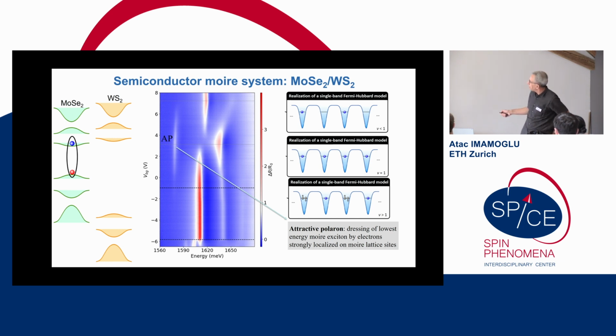Now, as we inject electrons, we see that interesting things happen, and we do not understand everything, actually most of the things. But what we do see is that there is an attractive polaron resonance that is appearing now at a more redshifted transition. What we can think about is that now we have these tightly bound electrons in the system, and we can make an optical excitation such that it is correlated with these. So if you want, it's a collective excitation of trapped trions, is one way of thinking about it.